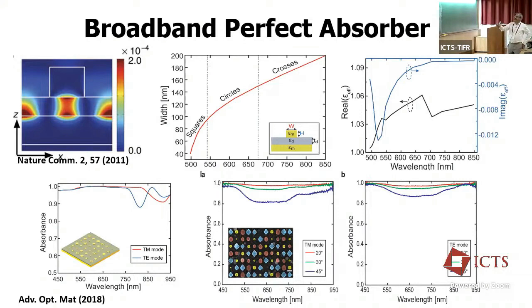There is a patterned metal surface on the top. There is a thick metal layer. In electrical engineering parlance, this is the ground plane where nothing can transmit through. If you make sure that the reflection is suppressed, which means nothing is transmitted, you have 100% absorption within this thin layer, which can be a few nanometers. We showed that for about a 10 nanometer thick silicon layer, we could get 99.86% absorption of the incident radiation, covering say the 450 to 950 nanometer region.